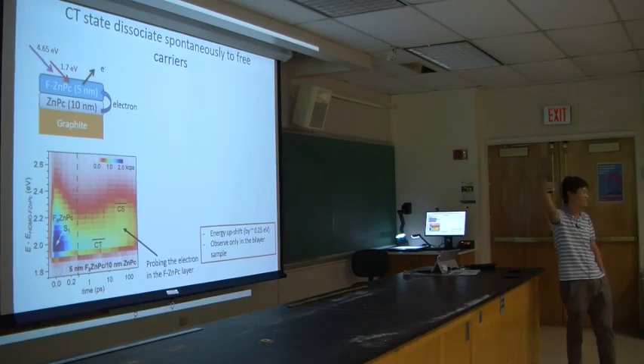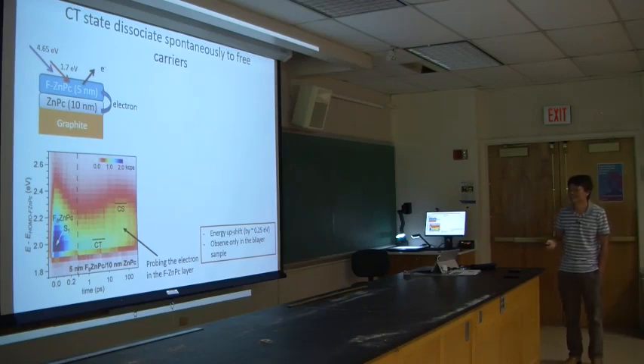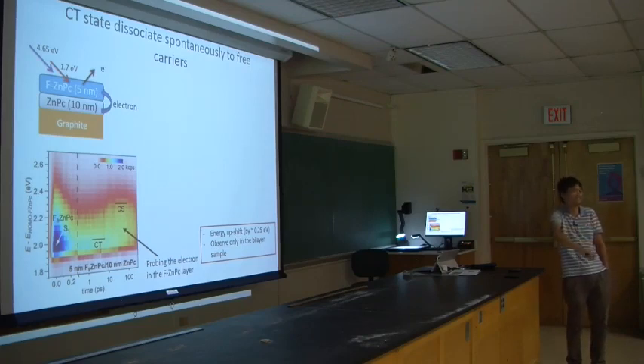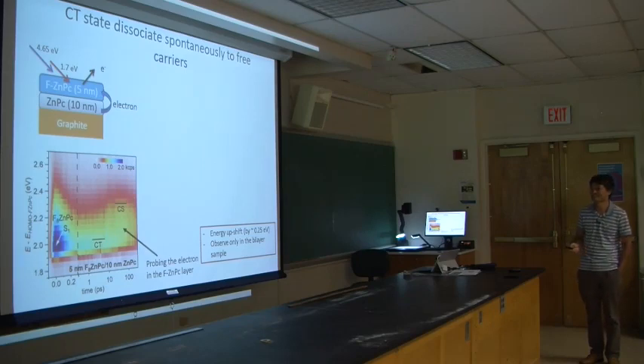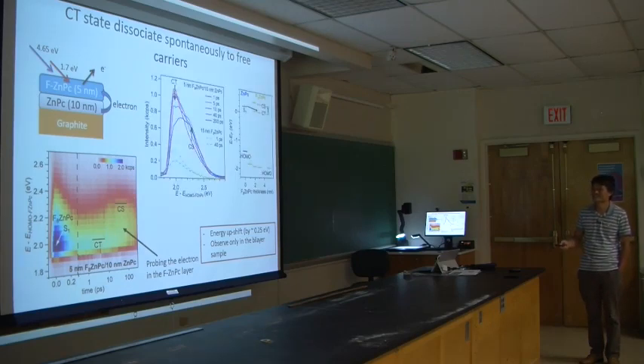But it goes up instantaneously, on a very fast time scale, right? So it's actually quite interesting, what's happening to that interface? You can go up in energy instead of going down in energy, because we know it always goes to a lower energy state, right? But here it's going up instead. So what's happening? It's easier to see in the spectrum. The lower energy state goes down, and then the hot state goes up, right? In the energy level diagram, this so-called CS state even has higher energy than the initial CT state, right?